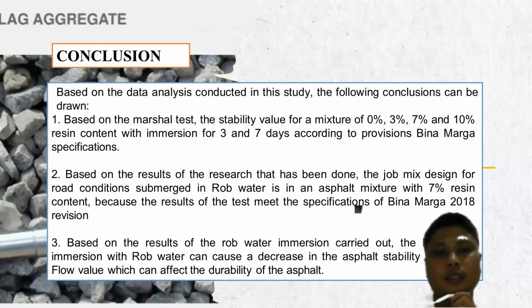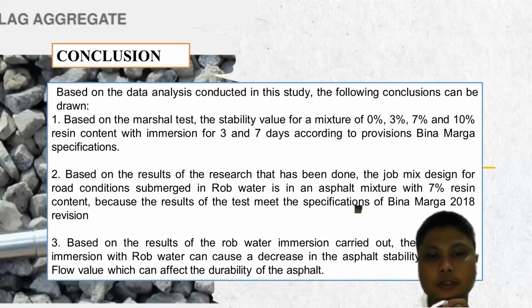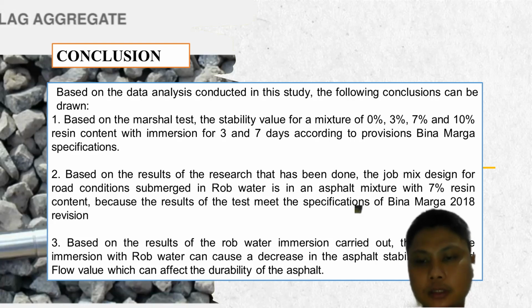The conclusion based on the data analysis conducted in this study, the following conclusions can be drawn based on the Marshall test. The stability value for a mixture of 0%, 3%, 7%, and 10% resin content with immersion for 3 and 7 days, according to the Marshall specification. Based on the result of the research that has been done, the job mix design for the condition submerged in Rob water is an asphalt mixture with 7% resin content because the result of the test meets the specification of Bina Marga 2018 revision.